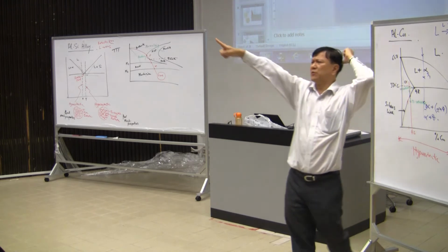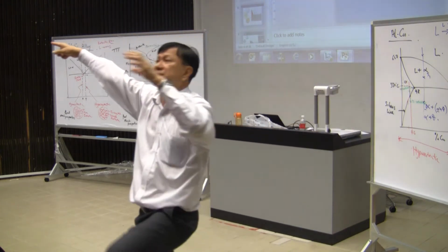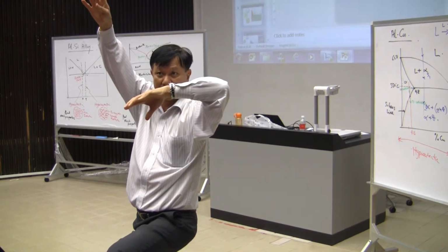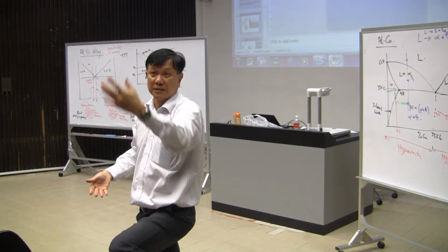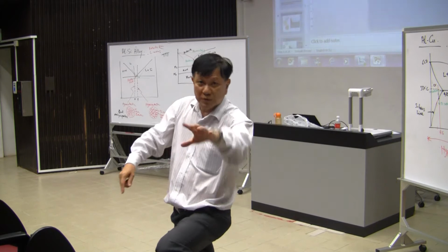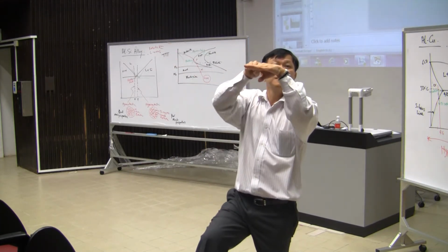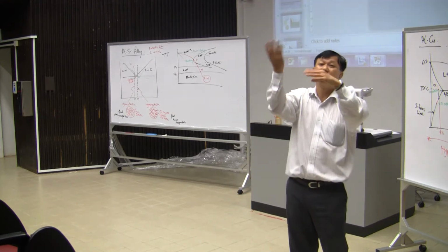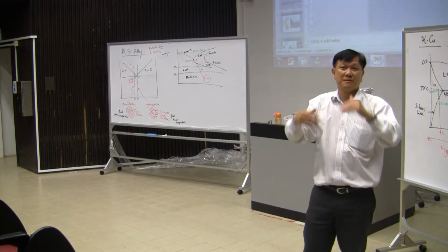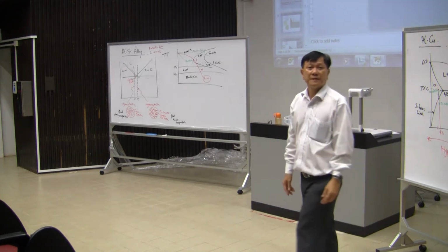From our heat treatment processes for steel, the first thing you do is austenitizing. Remember? I told you, heat to 830. Then after that, depending on your cooling rate, you get different processes. So you can redo all those, but tempering is below 723. You don't get any austenite below that.